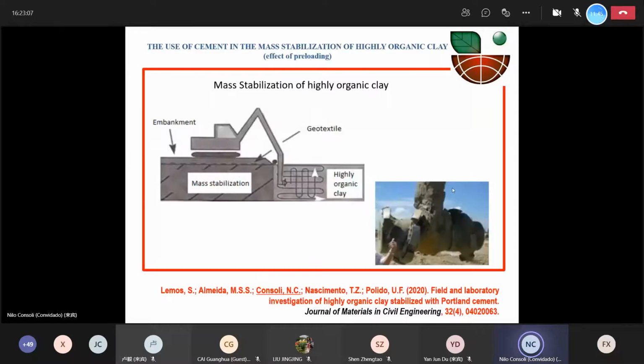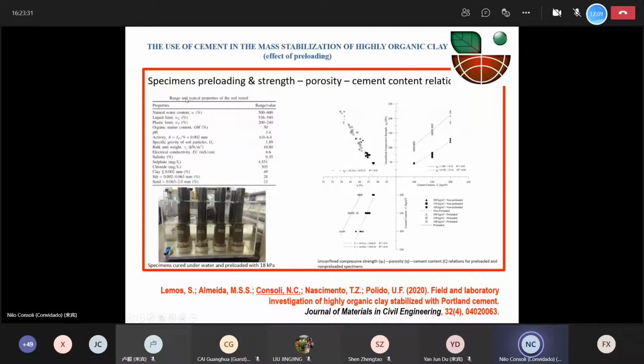Another problem that we also have to look after here in Brazil, which is quite common, is the possibility of using mass stabilization, mainly in highly organic clays. So we can see here this idea of mixing some kind of cement in the organic clay. This was a case just to give an idea; this specific soil was in the city of Rio de Janeiro. In this material, we have about 50% of organic matter content, and the natural water content was ranging between 500 and 600%, about the liquid limit or even above it. In this case, we also have problems with sulfate, and the pH was quite low. So it was really a difficult soil to deal with.